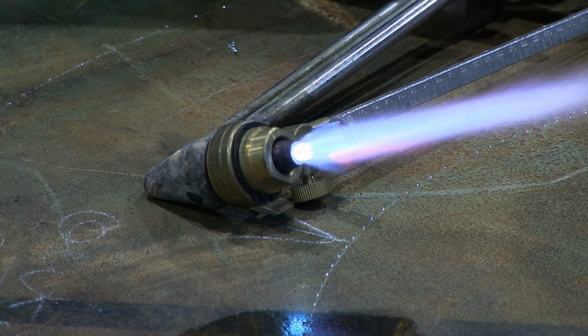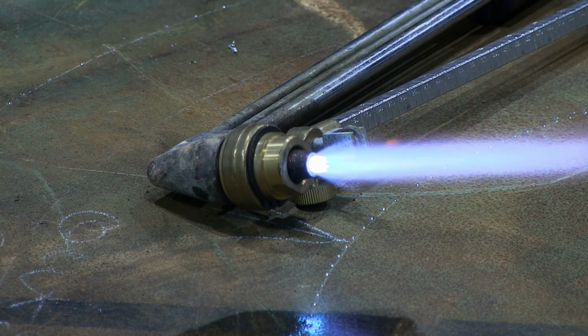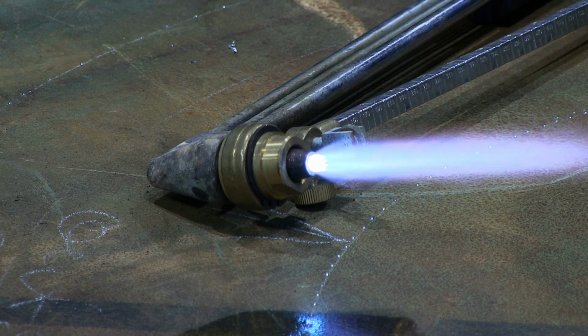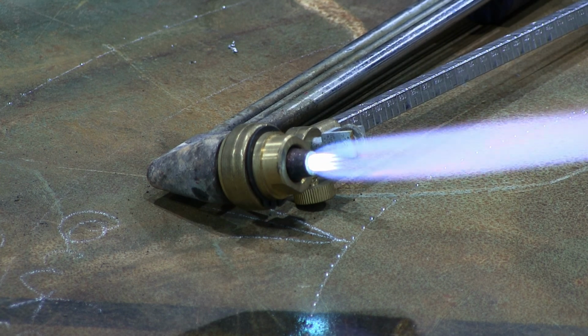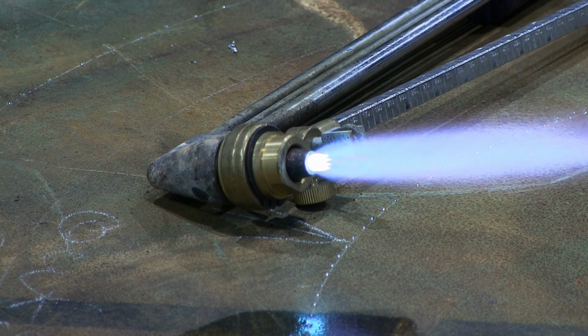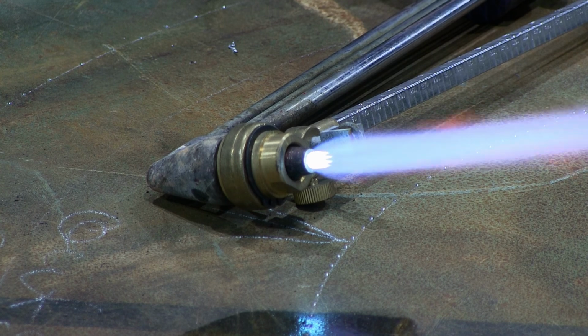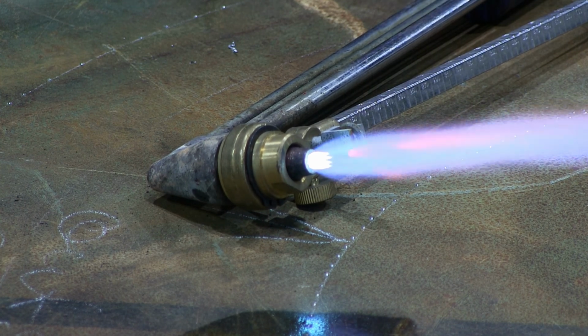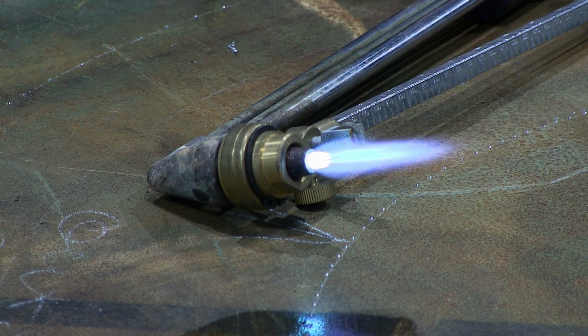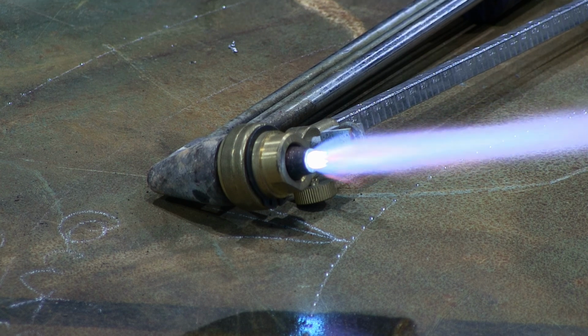You want your really hot flame not to grow every time you hit oxygen, because if that happens, that means your oxygen pressure is slightly too low, and you want to be able to maintain the heat while you're cutting with your torch. So when you adjust your mixture just right, you will see the distinctive glow in the brightest, hottest part of the flame, right at the end of the nozzle. It starts to have a very distinct glow to it.